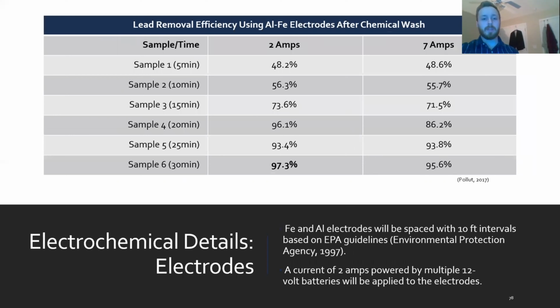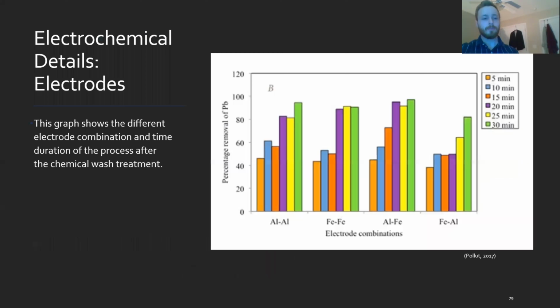Up next would be the efficiency of using aluminum and iron electrodes after our chemical wash for the electrokinetic reactor, of which we compared running 2 amps and 7 amps in our electrokinetic batch. Based off of this, we saw that the 2 amps had the highest removal efficiency of 97.3%. And this is with the aluminum and iron electrodes being spaced within 10-foot intervals based off the EPA guidelines. Here's a graphical representation of these electrode combinations based on different time frames.